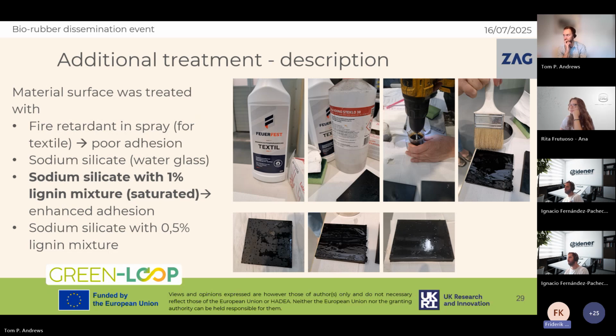What we found out is that the commercial material did not work with rubber very well, and actually did not stick at all on the material. So it's impractical. However, water glass, known to be good fire retardant, was already adhering to the surface, but when adding lignin, and we were able actually to add only 1% of lignin by weight, made the adhesion much better. So this seems clearly to be the way of treatment of the surface in order to enhance fire performance significantly.